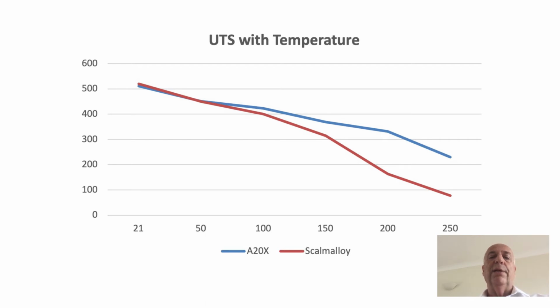You'll see that there's the ultimate tensile strength. The units are on the left, the megapascals, and this is comparing what would be considered at the time the highest available high strength aluminium powder. And as you see, once you get above 120 to 150, any additively manufactured part manufactured from a base of aluminium, silicon, magnesium starts to lose its properties rapidly and cannot be used at those temperatures. What we found on the heat treatment side was we had to heat treat up to 190 degrees centigrade as opposed to conventional aluminium powders at 160. And what we also found is that you can use this powder in a situation where the temperature could go to 180 to 190 degrees, a significant advantage.